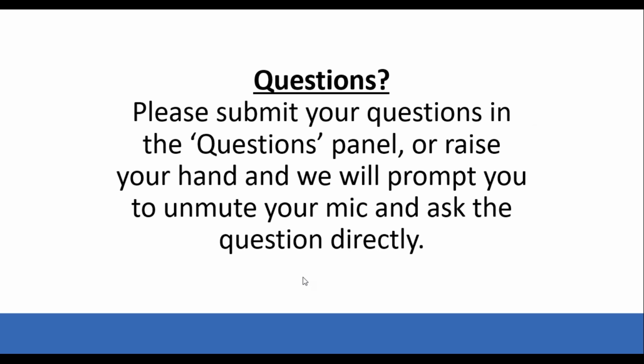Right, thank you. We have another question here. So let me just pull it up. What would be the minimum sample mass for a DVS experiment? We have two different configurations of the balance. So the low mass balance has a high resolution so that we can use a smaller amount of sample, between 1 milligram up to 150 milligram, and up to 1 gram of the sample with some counterweights. And we also have a high mass balance with a little bit lower resolution, but we can put up to 5 gram of the sample for the measurement.